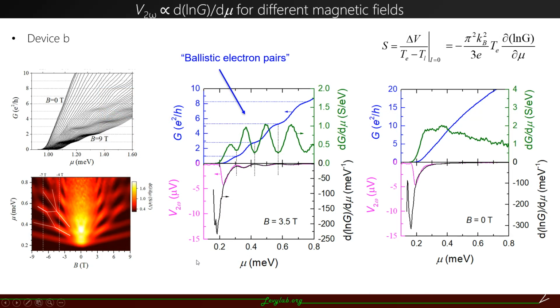So this is an example of the results we have measured. We compare the thermal voltage V at 2 omega with d log G / d mu in the same plot. We see that they compare quite well, with the peaks and the valleys corresponding to each other very well, showing a linear relationship between them, irrespective of the magnetic field, whether it's 3.5 Tesla when they are electron pairs, or 0 Tesla when the quantum wire is superconducting.